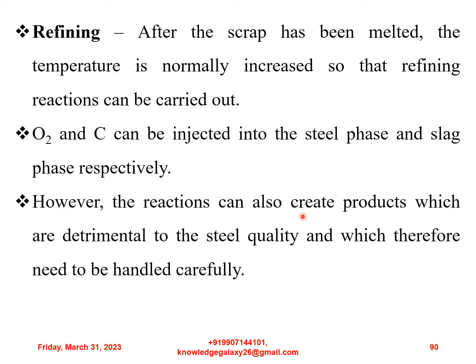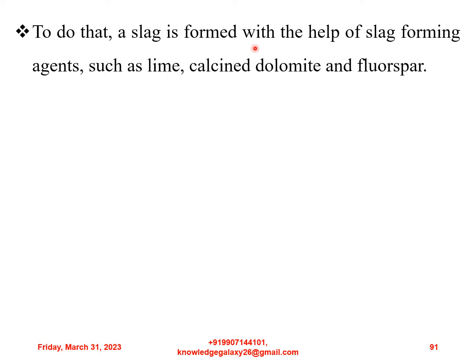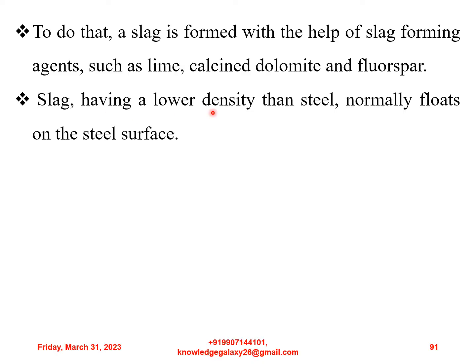However, the reactions can also create products which are detrimental to the steel quality and which therefore need to be handled carefully. To do that, a slag is formed with the help of slag forming agents such as lime, calcined dolomite and fluorspar. Slag, having a lower density than steel, normally floats on the steel surface. In addition to absorbing impurities from the steel, the slag also protects the steel from the atmosphere. So these are the major advantages and functions of slag in steel making.